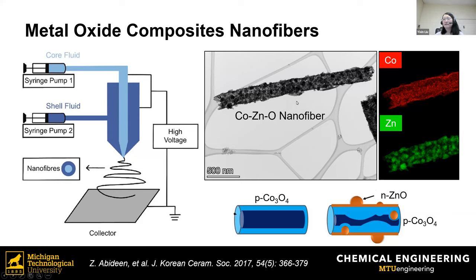This is one of the images from the TEM, the transmission electron microscope. Riley used cobalt zinc oxide, I think cobalt was the core. For this batch, we didn't get the perfect core shell structure, but as you can see here in the elemental distribution, the zinc is pretty much on the outside, and they tend to aggregate into those smaller nanoparticles.